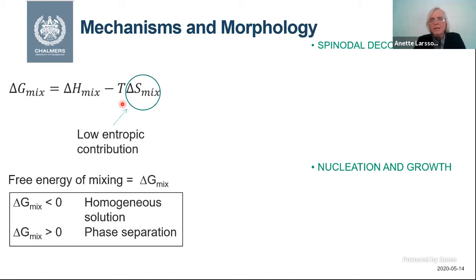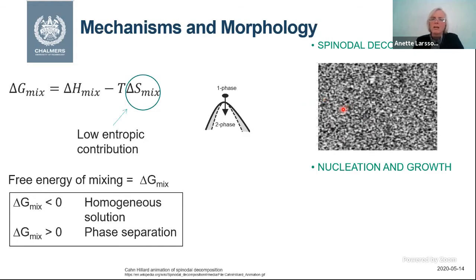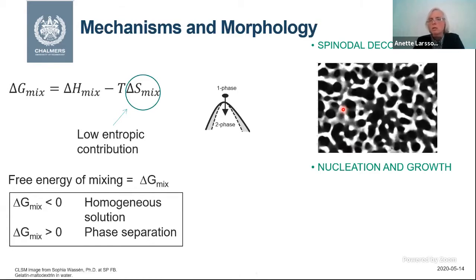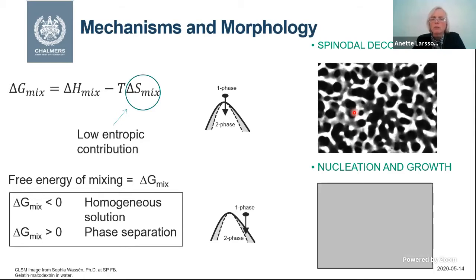But there are different mechanisms by which phase separation can occur. One is spinodal decomposition. So you start in one phase region and go to this two-phase region, and then you have this structure developing. You can see how it grows, and at some point it locks. And this picture is from Sofia Wassén at SP, and she was also working at RISE. But you can also have nucleation and growth, where you start in the one phase region, and you get to this region where you have nuclei that start to grow and grow and grow. And then you will get another type of structure, morphology, in the end.